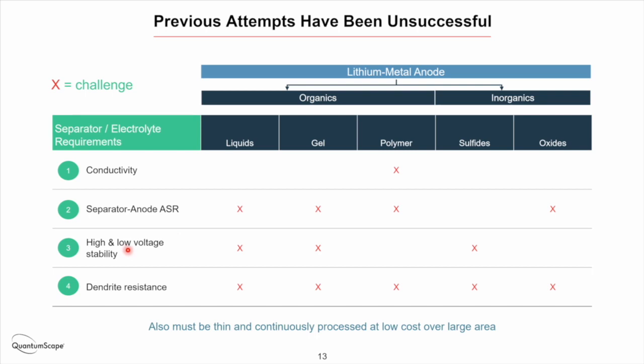The separator is going to be in contact with the anode and cathode over the life of the cell, and also in contact with both the 0 volts relative to lithium on the anode side and the high voltage of the cathode side. So maintaining stability over that very wide range of activity of lithium. It's about 80 orders of magnitude of lithium activity when you go from 0 to 4 volts. 80 orders of magnitude is such a large number. It's literally an astronomical number. There's something like 10 to the 80 atoms in the universe. So the 80 orders of magnitude of lithium activity, it's like saying you have metallic lithium on the anode side and 10 to the minus 80 lithium activity on the cathode side would be one atom of lithium per atom in the universe. It's just a huge range of lithium activity. So for a material to be stable across that full range is extremely challenging.